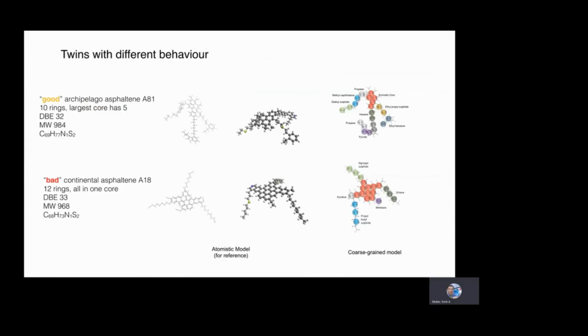The difference relies on the way that the aromatic rings, or the polynuclear aromatic rings, are ordered. You can see from this molecule how we've built an asphaltene molecule out of pieces. They're both Frankenstein molecules built from smaller pieces, which we recognize when we look at the fully atomistic description of these molecules. It would be extremely difficult to isolate these molecules and try to fit them, to find volumetric properties of them, which we could fit with the equation of state. So in this case, it's very obvious that this group contribution approach to these larger molecules makes a lot of sense and allows us to build molecules from smaller building blocks.